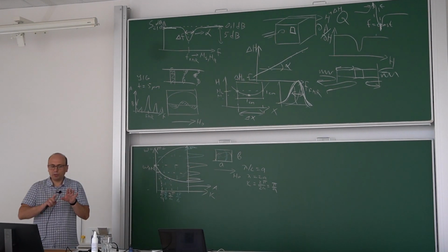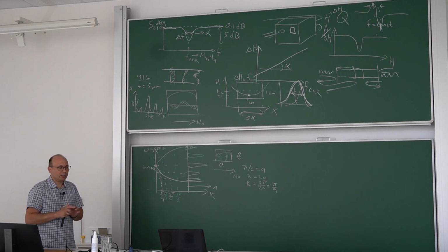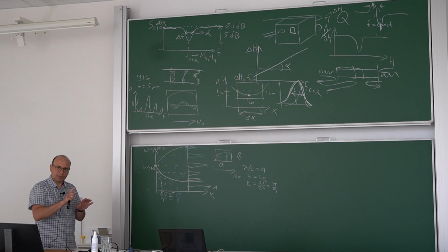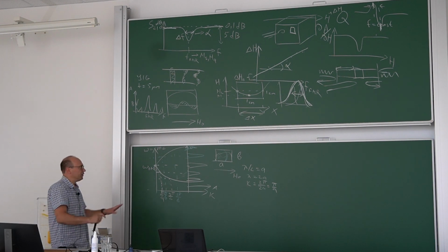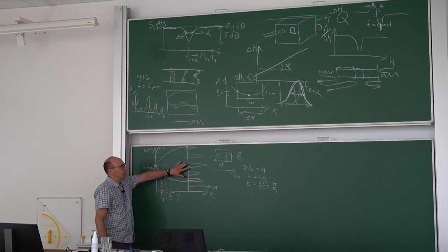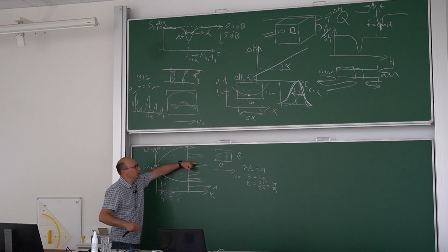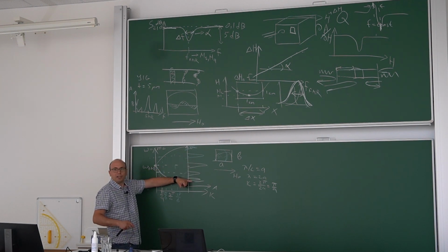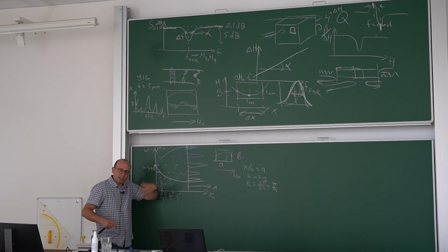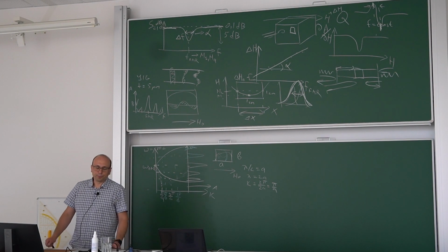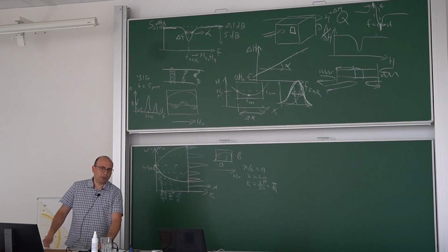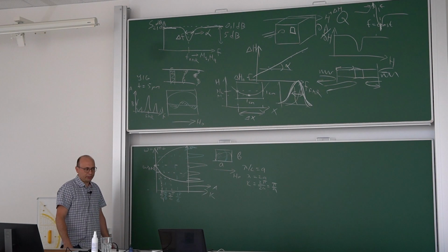But the absolute value in theory and experiment may vary, I don't know, by 50 Oersted or something easily, which people just associate with anisotropy. So it means that if you have some given field, you measure some frequency, you compare it to theory, and you see that your FMR is not sitting here but here. This delta you can easily attribute to anisotropy, one of the anisotropy components, or simply saturation magnetization.